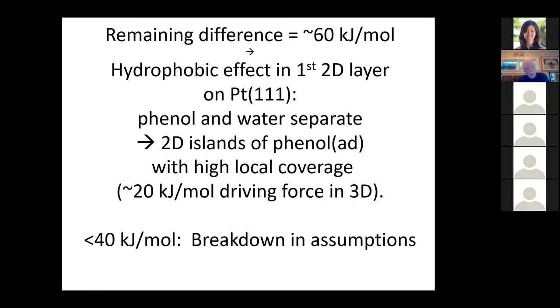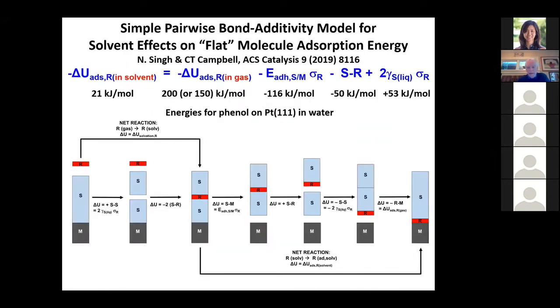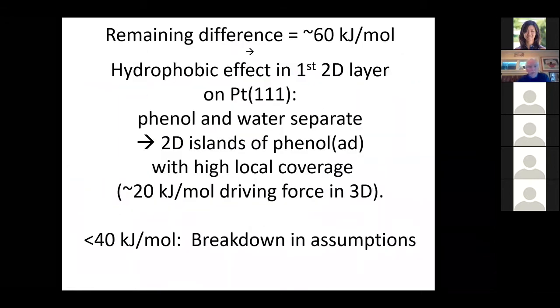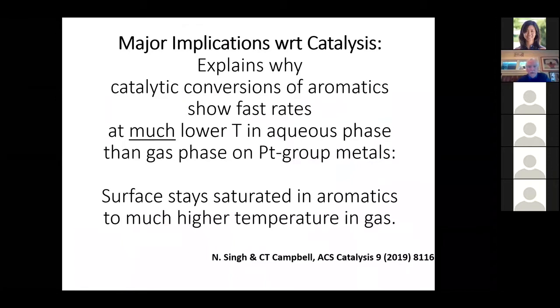Because remember, to start with, we were trying to explain the difference between 200 and 20 for the heat of adsorption. And so we've gotten most of it out of this picture that I drew there by simply considering the adhesion energy of the solvent to the surface and the other sort of water or solvent organic bond effects. The dominant one is the adhesion energy at the surface.